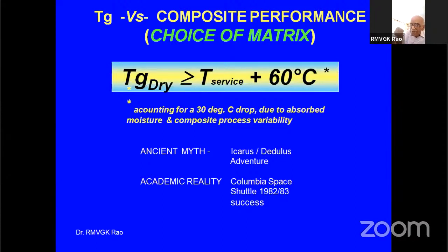Moisture absorption is to be reduced, but cannot be avoided totally, because when a flight vehicle or a vehicle in the open environment performs for so many years, it will pick up some moisture. So that moisture is bringing down the Tg, and if your ambient temperature goes above Tg, then it is a disaster, whether aircraft or even a ground-based radar. Therefore, that margin of 60 degrees should be there, and there are processing variables.